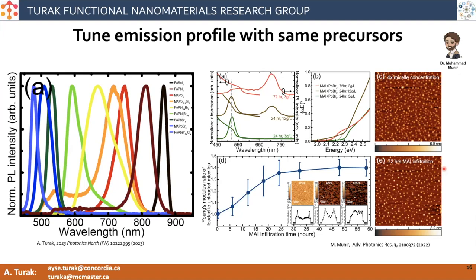And this is sometimes tricky because the problem is that the XRD is tricky in the system because they're small, and it's a little inconclusive because the micelle puts pressure on the crystal, and when you form it, it forms kind of unusual states at the end of the set. So something is definitely happening in these systems, but these are things that we're trying to explore.